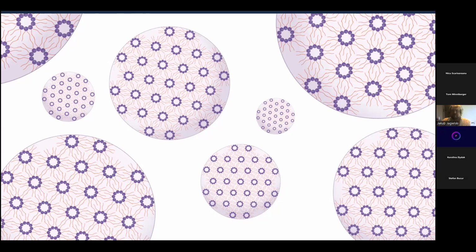Kinetically, these nanoparticles are stabilized by a surfactant corona. Typically, we use the triblock copolymer Pluronic F127. You can also observe in this schematic that these nanoparticles are polydispersed, so we have different sizes, not just one defined specific size.